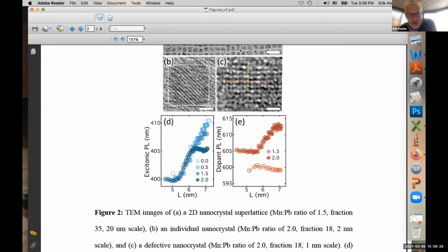The gap gets smaller as you get bigger. But if we forget about formation of exciton and consider it as a particle in a box independent of bound electron-hole states, by the way, there is a big dielectric constant, and probably the exciton binding energy is not as big. So it is heavily screened by epsilon around 1000.